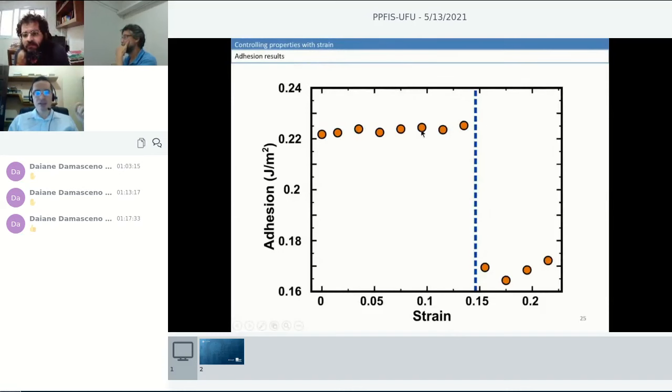And you can see here, as I repeated this process for higher strain values, as we expected in the beginning, when the material moves out of the plane, we have a large decrease in the adhesion, by about 30%, the decrease that we get when we have this kind of ring rotation out of the plane. So we really get a decent amount of adhesion.